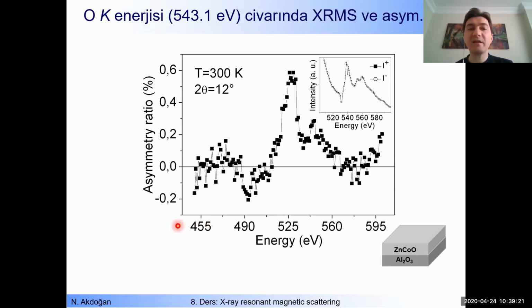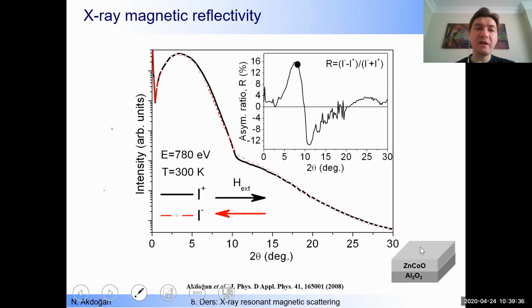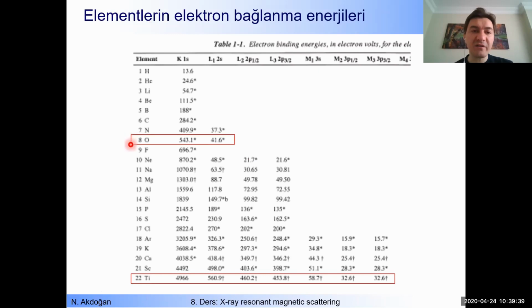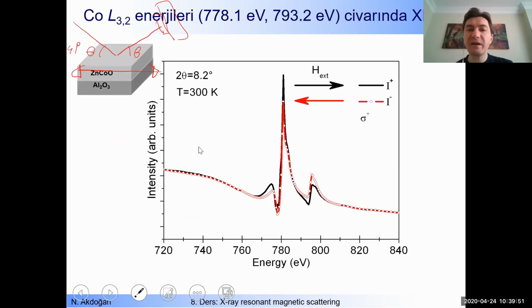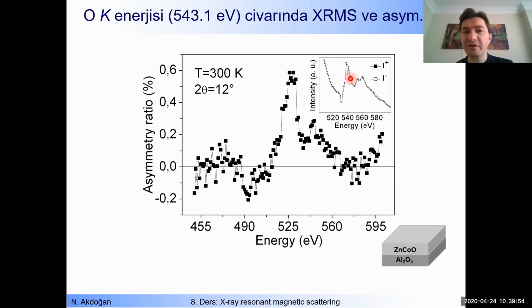Here we have another XRMS experiment. This is the energy range, okay? It starts from 500 electron volt and goes to 600 electron volt, and we are looking for the oxygen. Let's go to the table for the electron binding energies. For the oxygen, the binding energy for the K shell is around 543 electron volt, okay? 543. So I have to scan that range. 543 is around here, so I should start earlier and finish later.